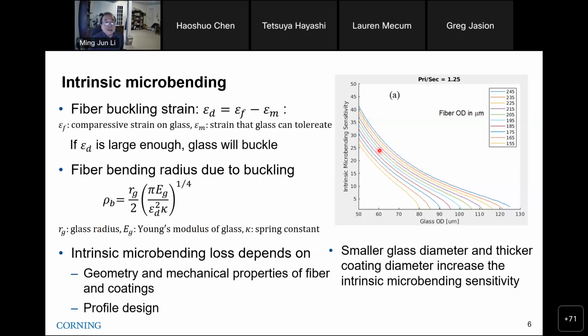On the right, the plot shows the model of the intrinsic microbending sensitivity. What you can see is that a smaller glass diameter and a thicker coating diameter increase the intrinsic microbending. For example, if we make a 165 micron coating diameter for the 80 micron glass diameter, the intrinsic microbending sensitivity